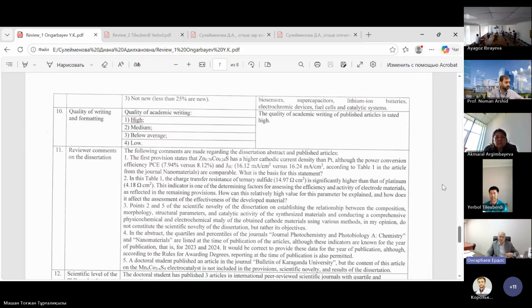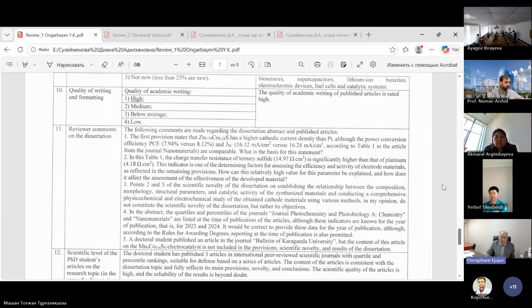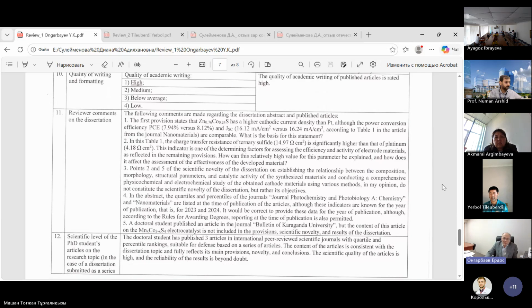First comment. The abstract states that zinc cobalt sulfide has higher cathodic current densities than platinum. Also, the power conversion efficiency, PCE, 7.94% versus 8.12%, and the JSC 16.12 mA/cm² versus 16.24 mA/cm². In Table 1 in the article from the journal Nanomaterials, these are comparable. So, taking into account the error margin and so on, what is the basis for this statement?